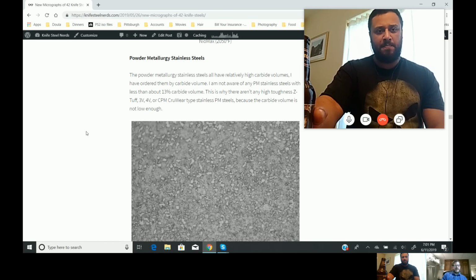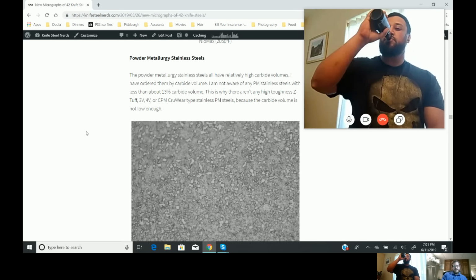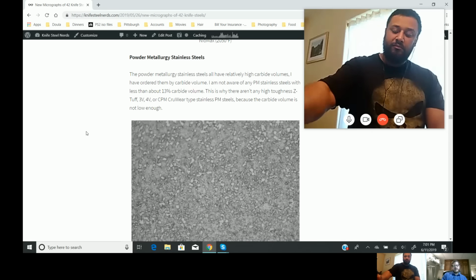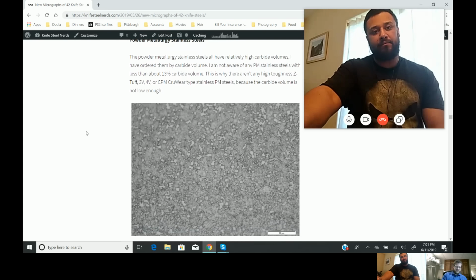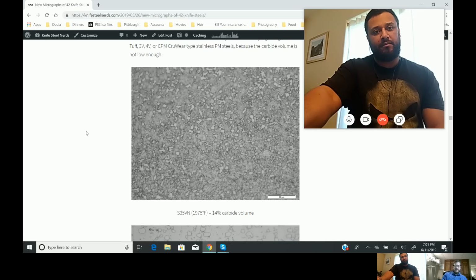A 10V steel has around 16% carbide volume. So the lowest carbide volume stainless steels are about as tough as 10V, which if you're talking non-stainless steels, no one thinks 10V is tough, but people argue all day long about S30V versus 20CV or whatever. They do. It's mind-numbing. But none of these have really that high a toughness because they have too much carbide in them. So here's an S35VN.